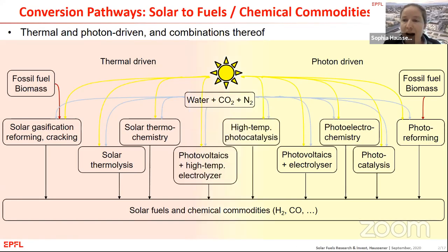And then, of course, you can imagine that you start to combine the approaches with high temperature electrolysis, for example, photo-driven, and you start to also enter a more interesting combined space. You can see a bit the difference between the approaches, which you can mostly characterize by temperature. So you see that the thermochemical approaches typically use rather high temperatures, while with photo-driven ones, typically you try to stay rather close to environmental temperature.